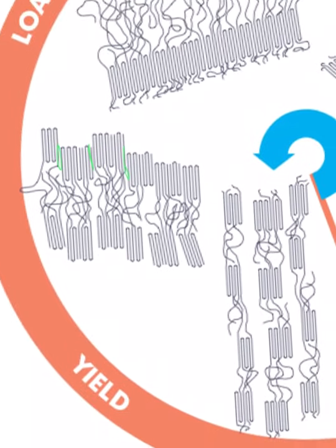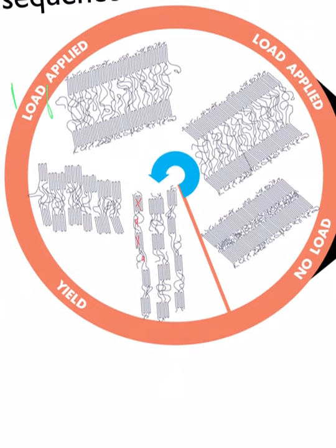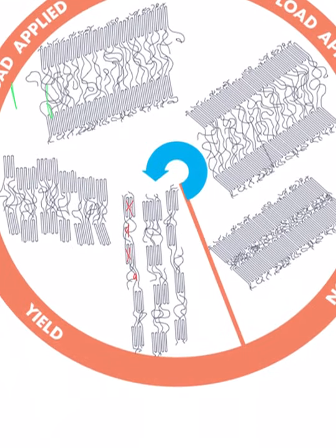And then as we keep extending this further and further, then we can really fragment things. And so we have little crystals here, and then amorphous in between them, and crystals here, and amorphous, and so forth. Okay, but this is the clock diagram. This is how we can think about these plastics deforming and the microstructure that is rearranging dramatically as we start straining this. We haven't broken any polymer chains at all. All right, we've broken and reformed 1 million secondary bonds, not covalent bonds. We haven't broken any chains.